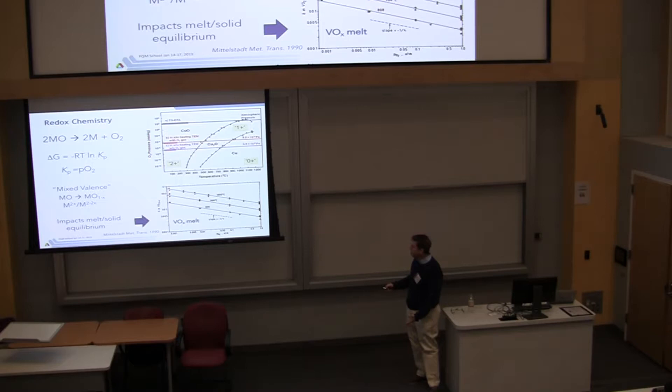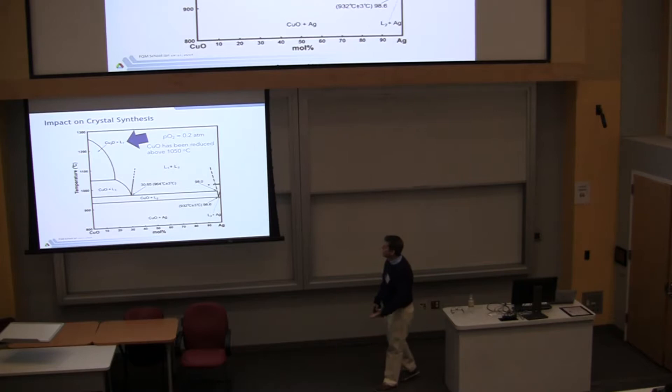300 bar is barely off the axis. So we're not doing much. If you want to do high pressure synthesis using pressure as the real driving force for doing something, you've got to go to big pressures. You've got to use cubic presses or octahedral presses or diamond anvils to grow things. So we know that you can make diamond by squeezing on graphite. But you've got to go to about 5 GPa and several hundred degrees or 1,000 degrees Celsius to do it.